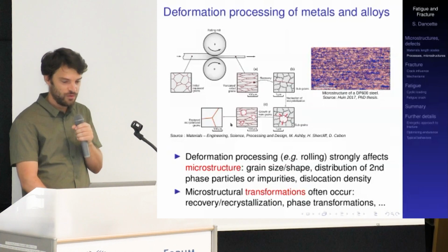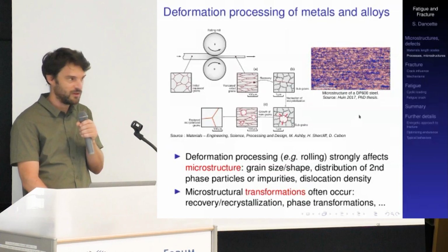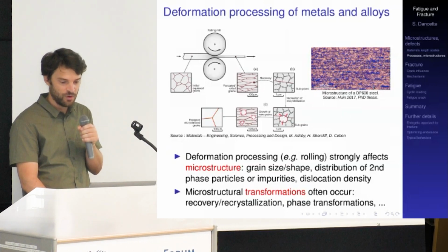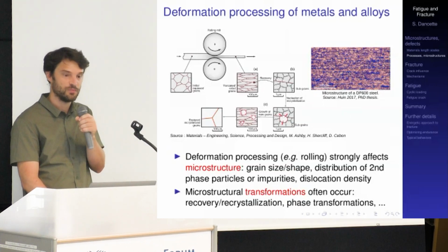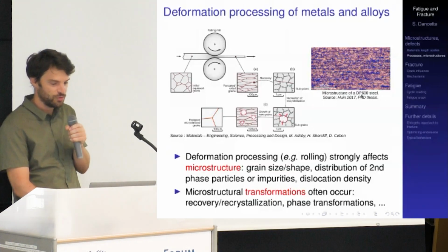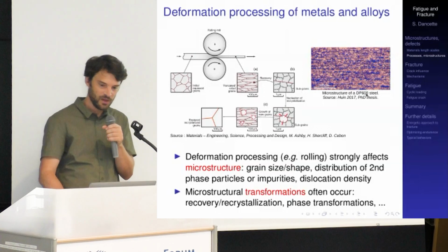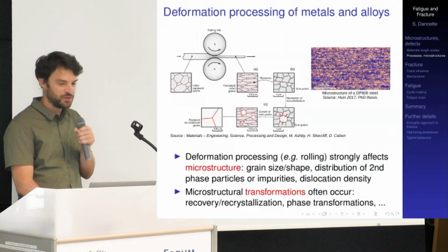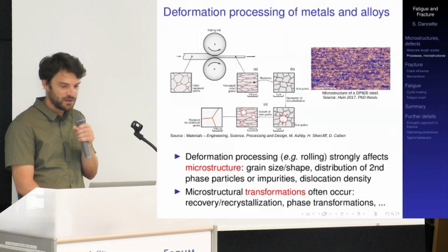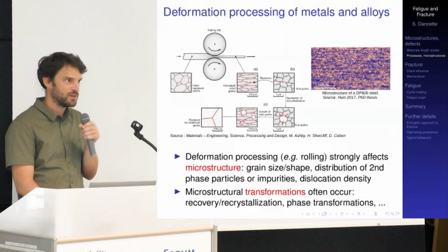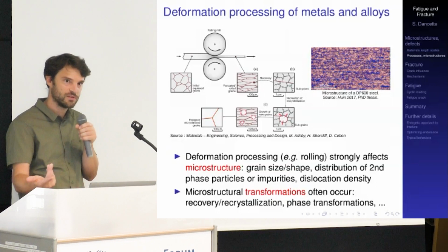And along the way, you may find different types of defects due to the rolling process, starting, for example, with alignments of second phases in the microstructure, as you can see here. So in that case, this is a dual phase steel, an automotive steel. And in this particular case, what you can see in black here, compared to the background, is the so-called martensite phase of steel, which is very hard and very brittle, providing a lot of strength to the material.